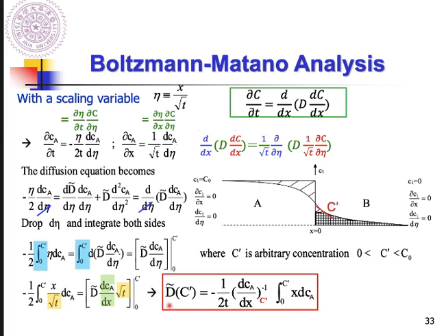How to get the diffusivity as a function of concentration of diffusing atoms. As long as when you perform your experiments, after diffusion for time t, you take your samples out and make a section, and use EPMA or SIMS to analyze the concentration of diffusing atoms as a function of location.